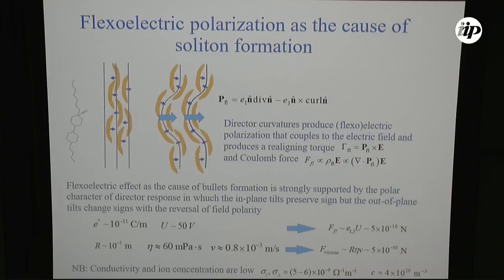One question is, electric field effects, as I demonstrated, have been studied in liquid crystals since the 1920s, 30s by Fréedericksz and then by many, many other people. So the question is why no one has seen these soliton formations. One possibility is that not only should the material be of negative dielectric anisotropy to cancel this dielectric response, but also the material must be sufficiently pure.